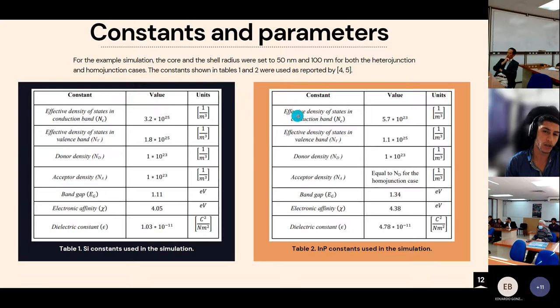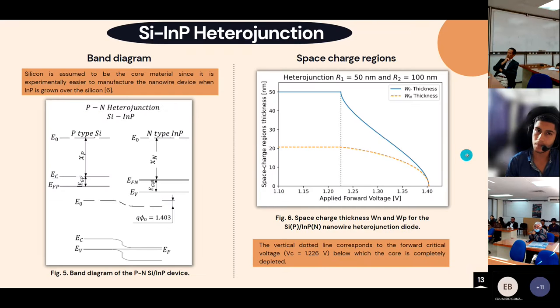In tables 1 and 2, we have the effective density of states in the conduction and valence bands for both materials, indium phosphide and silicon, the donor density, acceptor density, and the gap, electron affinity, and dielectric constant for both materials used in the simulation. For the silicon indium phosphide heterojunction, silicon is assumed to be the core material, since it's experimentally easier to manufacture the nanowire device when indium phosphide is grown over the silicon.